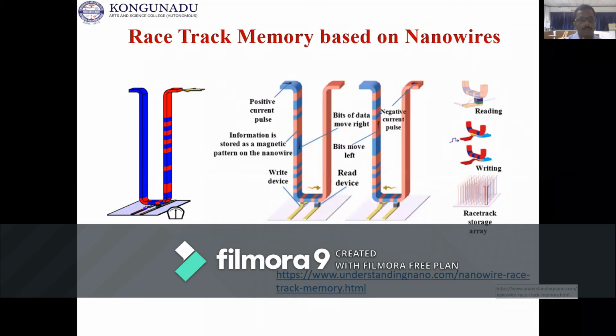So if we look at this, magnetic nanowires embedded in a U structure, where the moving layers are called magnetic domains. By moving the magnetic domains, you can store data: you write data by applying a positive current pulse, which moves the magnetic domains and stores the magnetic data. And when you apply a negative current pulse, opposite to the positive one, you can read the data. You can write it on a nanosecond or microsecond scale. So you can read, write, erase, copy, and everything in a few microseconds. So you can transfer data in gigabytes and terabytes in a very short time without losing any data. So we are using magnetic nanowires. The areal density also is increased.